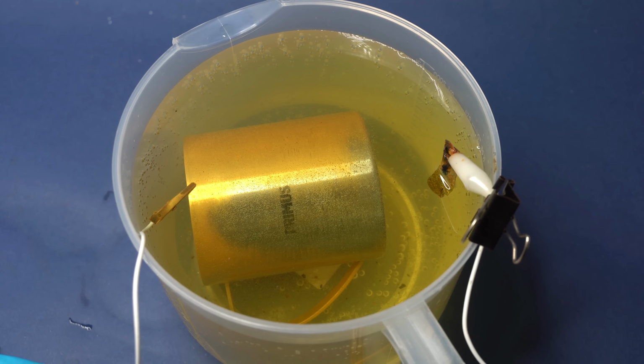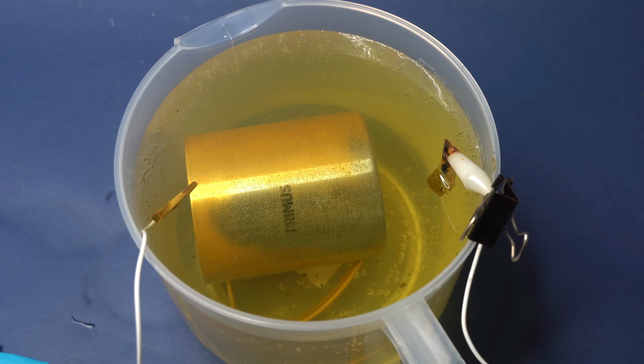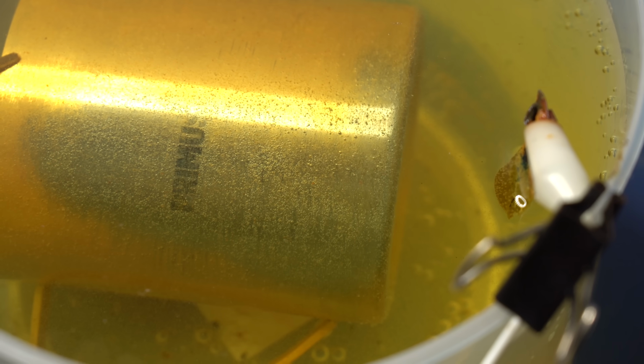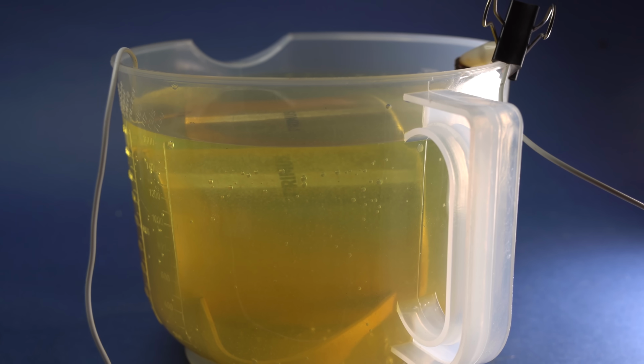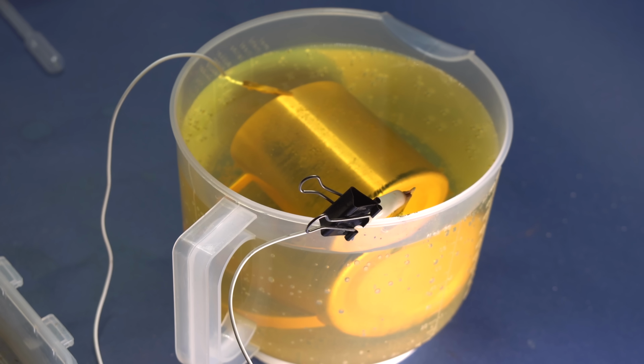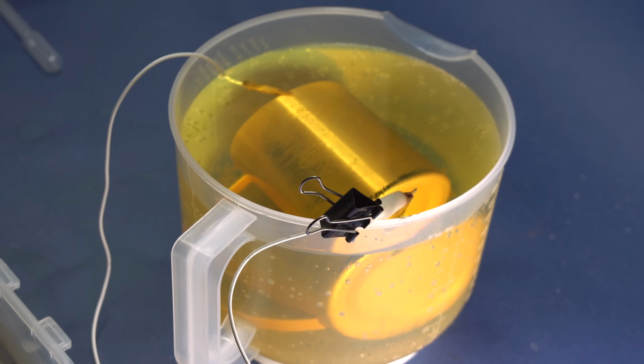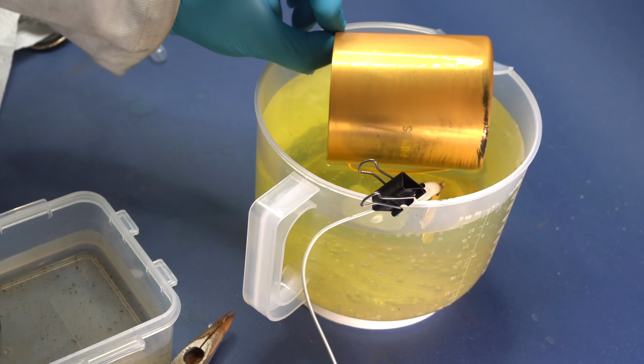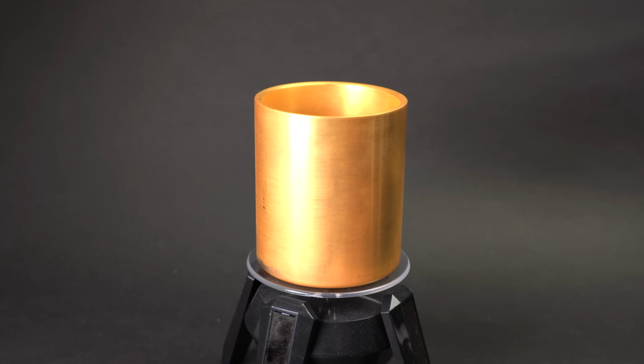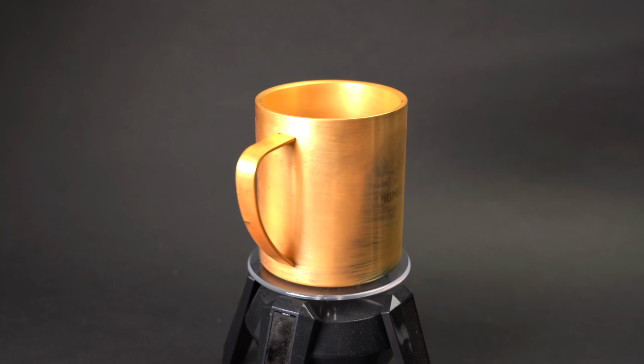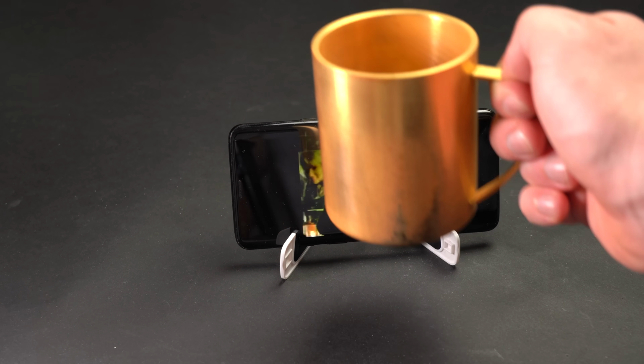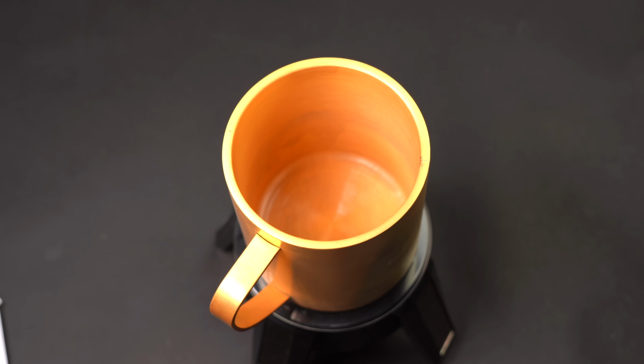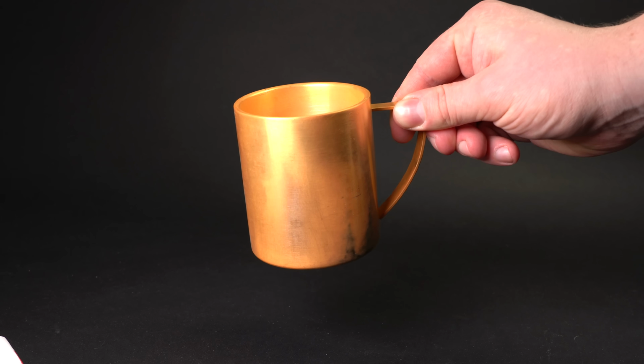After that, I diluted the electrolyte with water in order to allow it to cover more surface. Now the cup will be gold plated more evenly, but it will take much more time because the electrolyte has been diluted. I left the cup in the solution for 12 hours and in the end it was coated in a thin and more or less even layer of pure gold. In the end, we got a beautiful looking cup plated with 24 karat pure gold. For me, it looks very amazing.